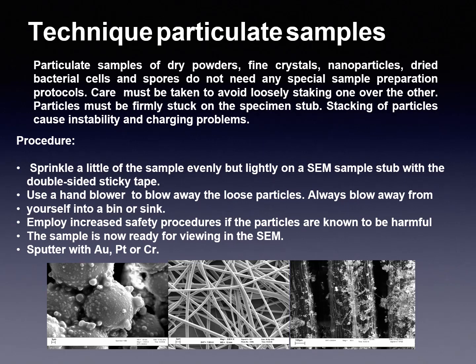Use a hand blower to blow away the loose particles. Always blow away from yourself into a bin or sink. Employ increased safety procedures if the particles are known to be harmful. The sample is now ready for viewing in the SEM. Sputter with either gold, platinum, or chromium.